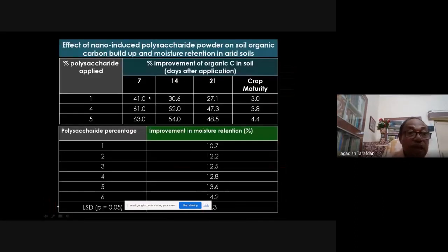You can see the carbon buildup. Polysaccharide is also carbon. So when we apply 1%, 4%, 5%, immediately after 7 days we see tremendous improvement of soil carbon, but gradually it declines due to the microbial effect also. If soil carbon builds up, microbial buildup also happens, so you get gradually less carbon buildup. But at crop harvest, the net carbon buildup you may expect is 3 to 4%. That carbon buildup you may expect with the application of polysaccharide powder.